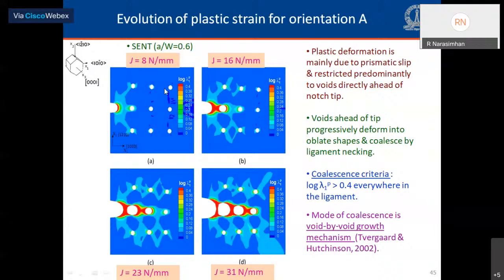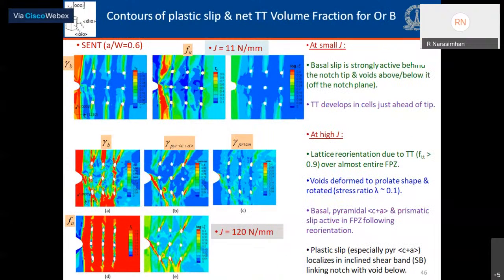And as J increases, it is restricted to the row of voids ahead of the tip. So these voids progressively deform into oblate shapes, strain localizes in the ligament, and then they keep necking down. So there's a void-by-void growth mechanism which is active for this orientation. On the other hand, we see a different picture for orientation B, where the C-axis is along the normal to the flat surface of the notch.